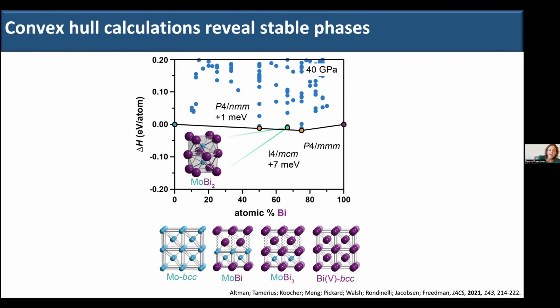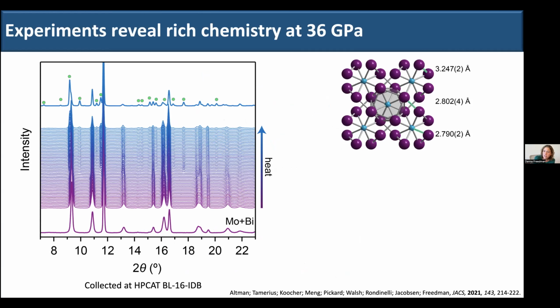And so what we identified right here is this molybdenum bismuth 2 phase. And we identified this at about 40 GPa. You can see that there are other structures that are less stable that we might find, but this suggested that 40 GPa could be a reasonable place to look for some structures. We also observed a collection of other potential stable structures in these calculations. And what I want to emphasize is that this approach is really a guide for synthesis. It says, where do we see these different structure types beginning to stabilize and what compositional ranges are useful?